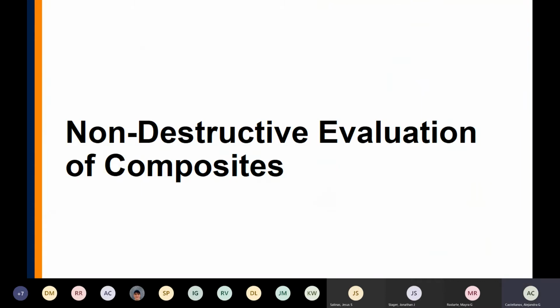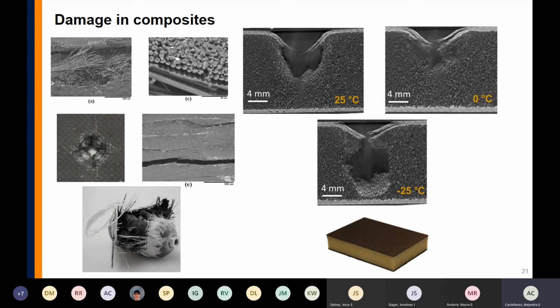Another project that I'm working on is the non-destructive evaluation of composites. As I mentioned, damage in composites is really hard to detect when there is not a very big damage that we could see, like a perforation, because you will always have fiber fracture, for example in letter A, letter C, in which the fibers are pulling out of the matrix, and then letter D, where the striker completely perforated that composite. And in letter E, we have delamination, which is the separation of the layers of fibers because the resin-rich region is very weak. So why are these a problem?